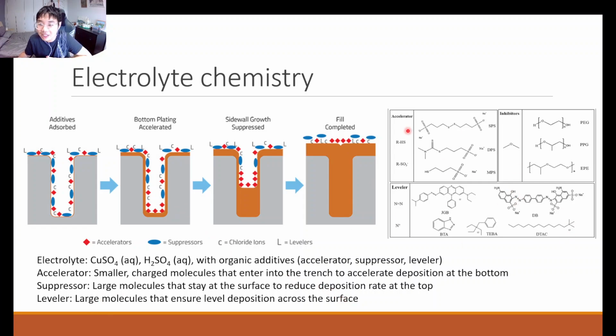Alright, and the leveler is similar to the inhibitor. That is a large molecule, right? Not really as large as your inhibitors, but also fairly large and bulky. And the purpose of this is to ensure level deposition across the surface, to ensure that the deposition rate doesn't occur too fast at one spot and too slow at another. Often, the right ratios and the right chemicals to be used for this is a trial and error kind of scheme. So it has to be determined experimentally what is the best ratio and best composition, because you can imagine that this is a very complex system for any first principles modeling.